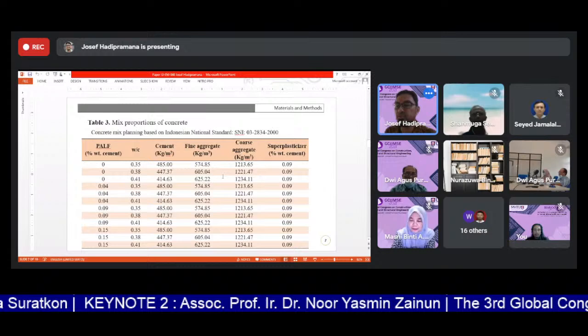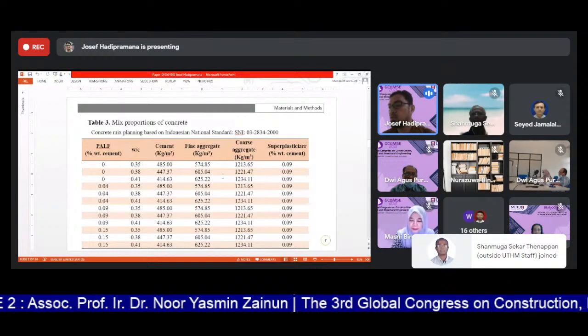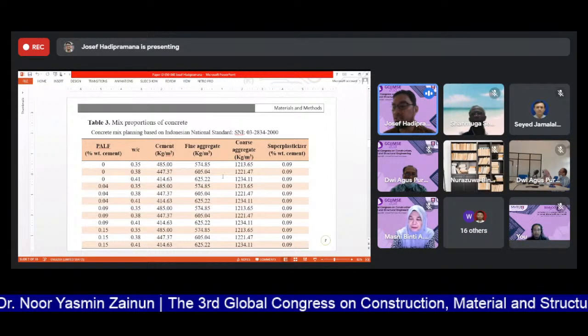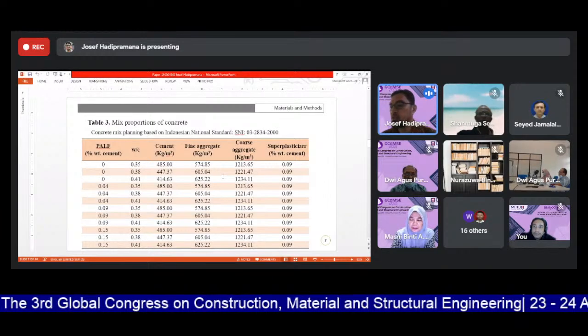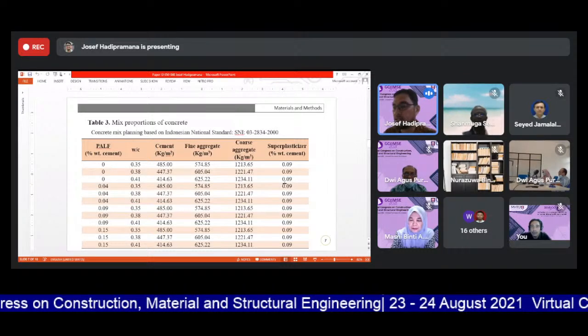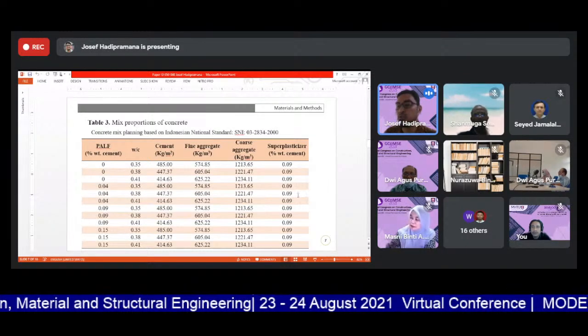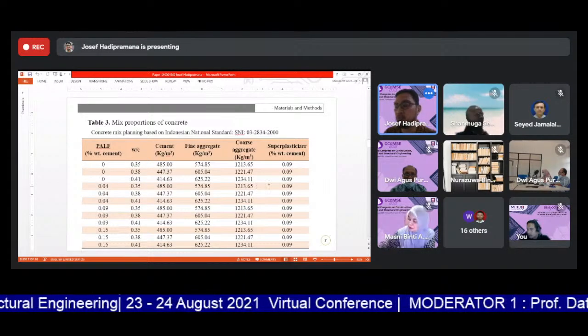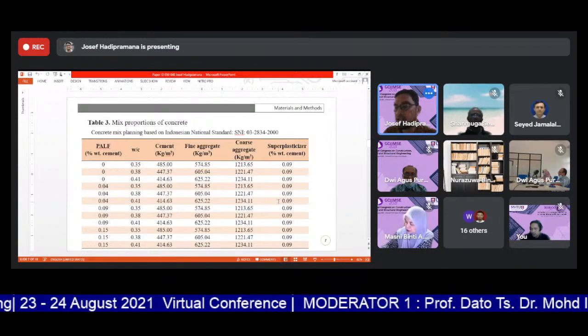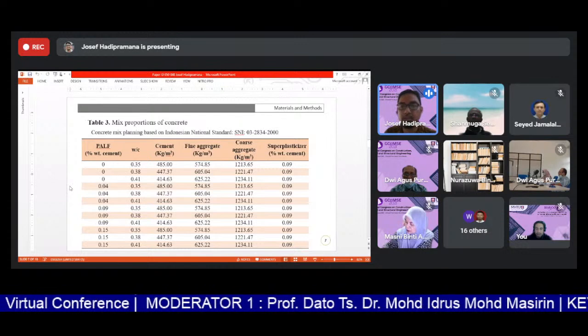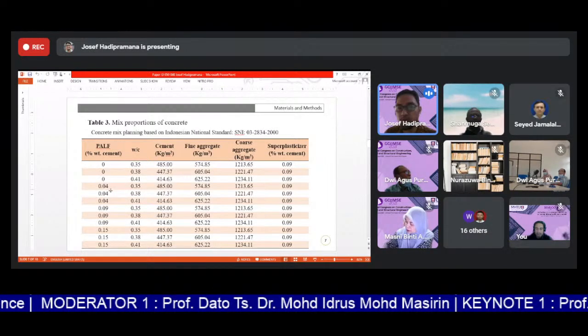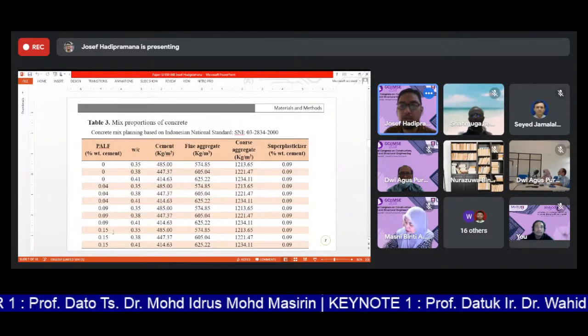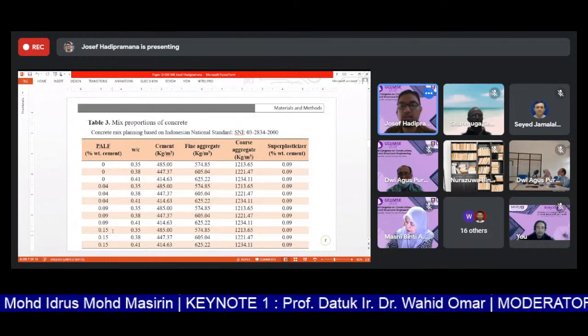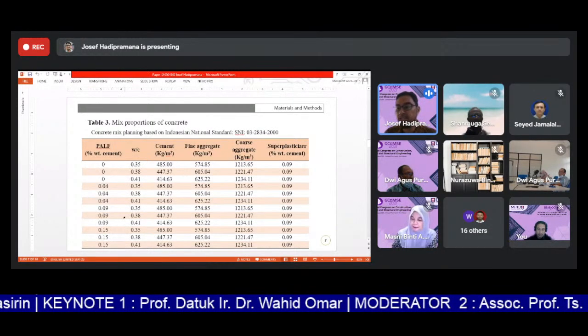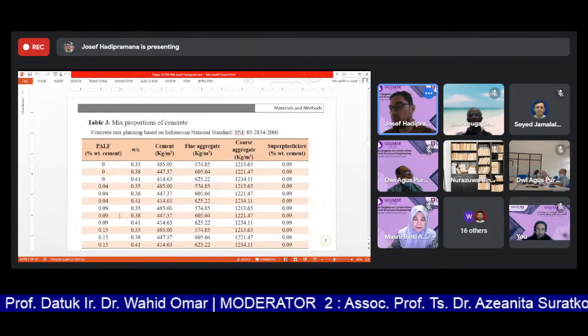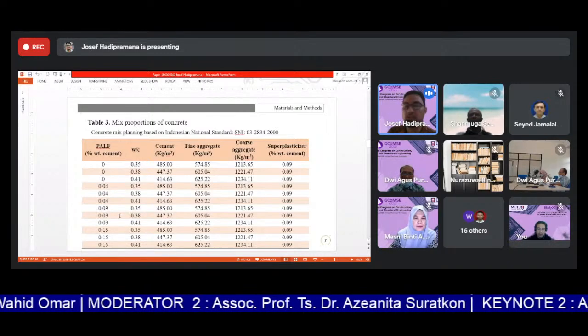To develop the high-strength concrete based on the Indonesian national standard, the composition of the proportion of each variation is as in table 3 here. In this study, we are using superplasticizer constantly. Superplasticizer helps the viscosity of the mixture so that the concrete can flow. In this case, there are 3 variations in the amount of PALF: 0.04, 0.09, and 0.15 of the weight of cement. Deliberately, fiber is not mixed in large quantity because it can interfere with the workability and moisture of the concrete.